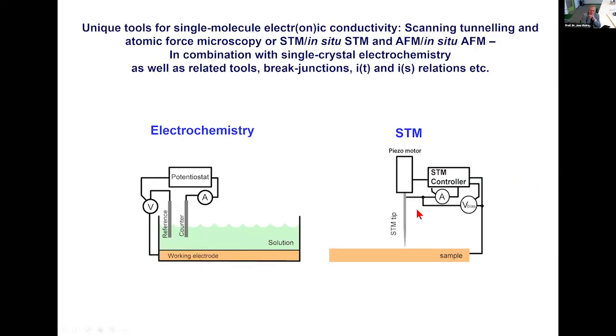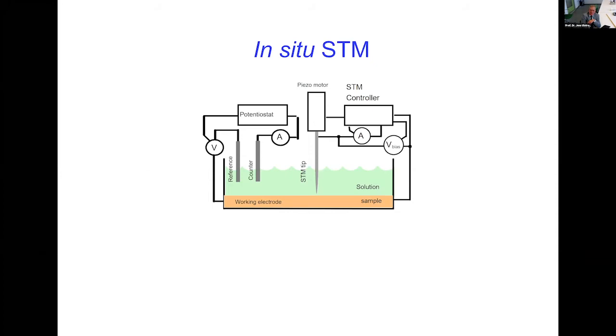In situ STM: in electrochemistry, we have a working electrode, a reference electrode, and a counter electrode. In so-called normal STM, we have a working electrode or sample and a tip. For proteins, we would like to study them in their natural aqueous environment, but we cannot just put water into the STM cell, because then we have no control over what is going on at the electrodes. There's no electrochemical potential control. So in electrochemical STM, we combine the two in such a way that we have the working electrode with potential control relative to the reference electrode, and the tip electrode controlled relative to the working electrode, which is again controlled relative to the reference electrode. So everything is under potential control.